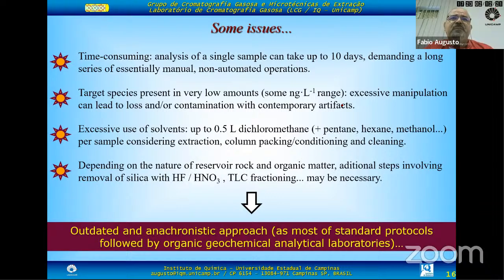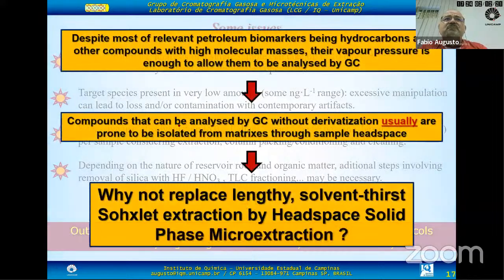Some of those species are present in nanogram per liter concentrations. You have to use very large amounts of solvents, up to half to 1 liter of dichloromethane per sample, lots of solvents and materials, and depending on the rock, you have to destroy the inorganic fractions with hydrofluoric acid, nitric acid. Sometimes you have to use thin layer chromatography as previous fractioning. These are very outdated, anachronistic approaches, but it's the standard for most of the organic geochemical labs.